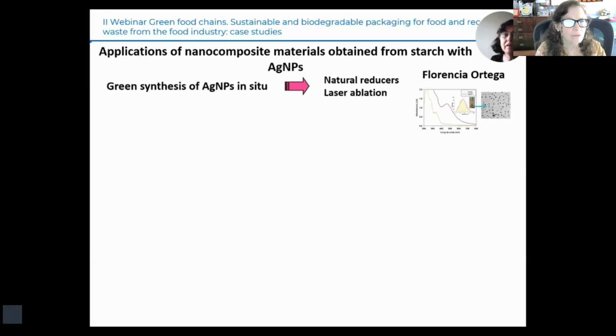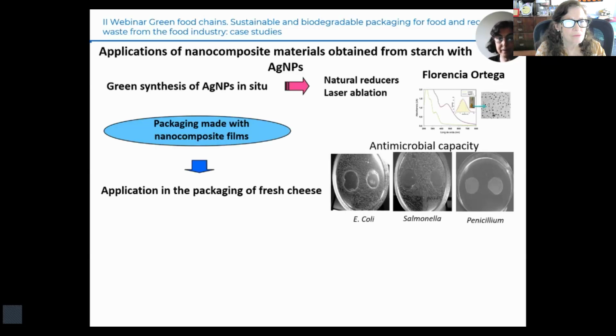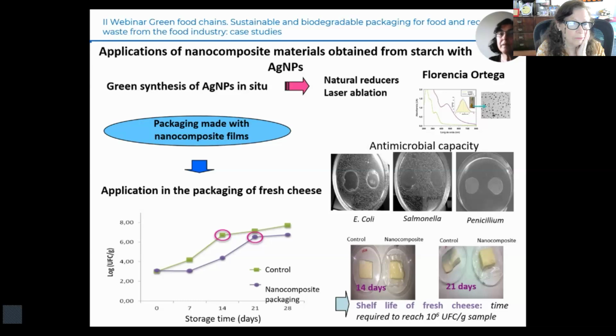As part of Dr. Florencia Ortega's doctoral thesis, silver nanoparticles were synthesized using green techniques in the film-forming suspension of cornstarch-based films. Natural reducing agents derived from lemon juice were used, and the nanoparticles were also obtained by laser ablation. Nanocomposite materials were developed and characterized for their relevant properties. The nanometric size of the nanoparticles and the antimicrobial capacity of the nanocomposite films were confirmed. Through heat sealing, bags were obtained and used for packaging fresh cheese, demonstrating their effectiveness in extending the product's shelf life by 7 days under refrigerated conditions.